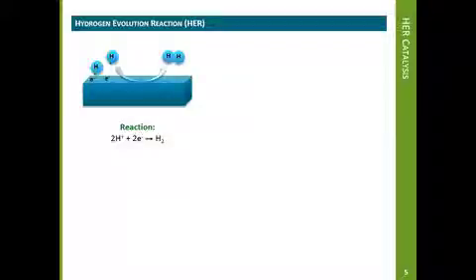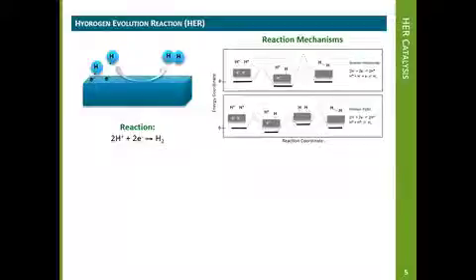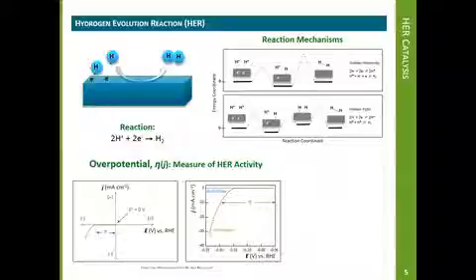Let's first take a look at HER, the simplest of the three reactions. Two reaction mechanisms are generally accepted, both of which feature chemisorbed atomic hydrogen as a critical intermediate prior to the release of hydrogen gas. These mechanisms remind us that the electrocatalysis of HER, as well as that of OER and CO2RR, is a surface phenomenon, whereby the slowest step involves the interaction with surface-bound species. One experimental figure of merit in assessing catalytic activity is overpotential.